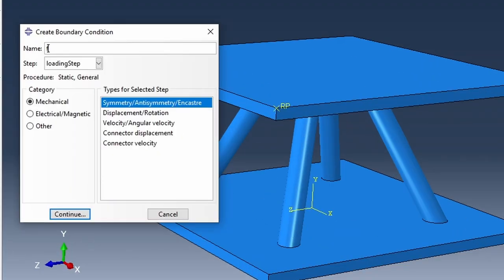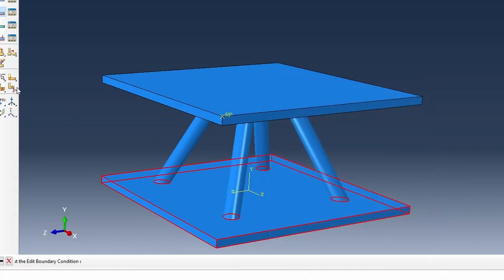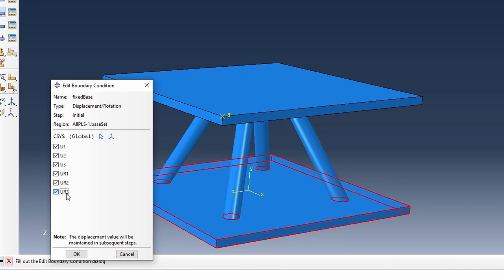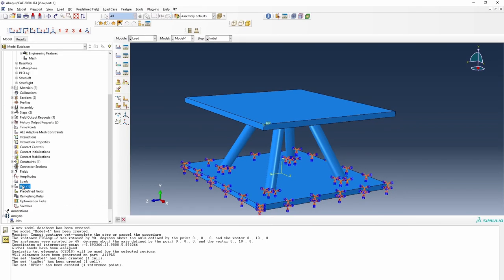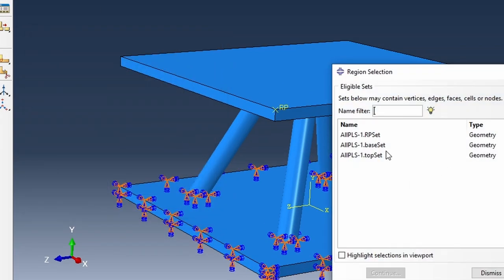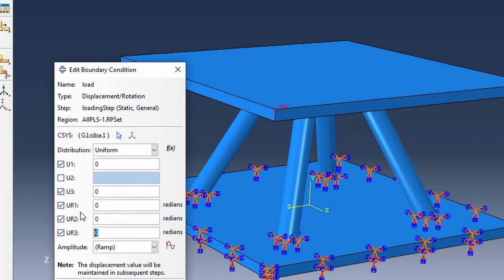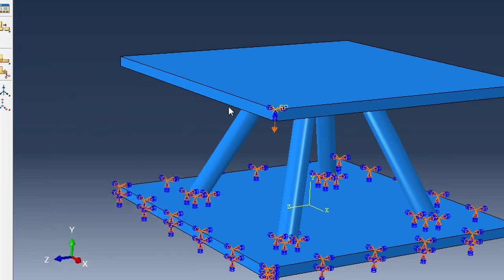Now we think about the boundary condition — we fix the base securely in all possible directions. Then we introduce our load associated with the loading step, applied on the reference point. This load acts only in the Y direction, with all other directions fixed. In the Y direction I'm making this minus 6, because the overall length is around 57mm, so approximately 10% strain.